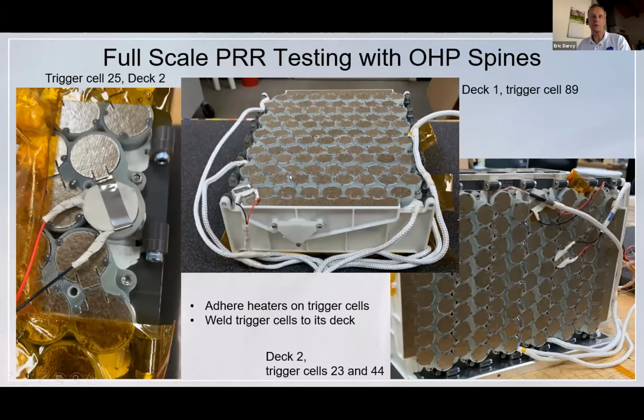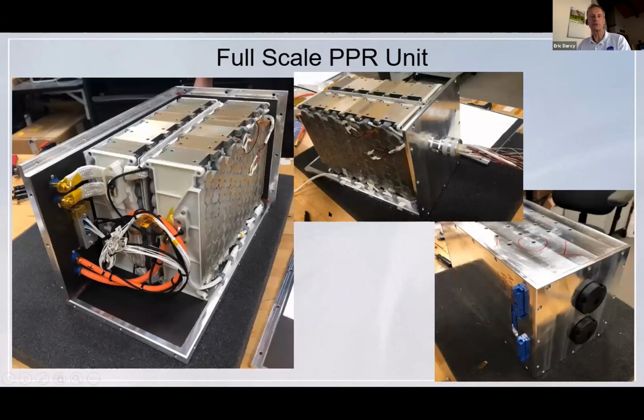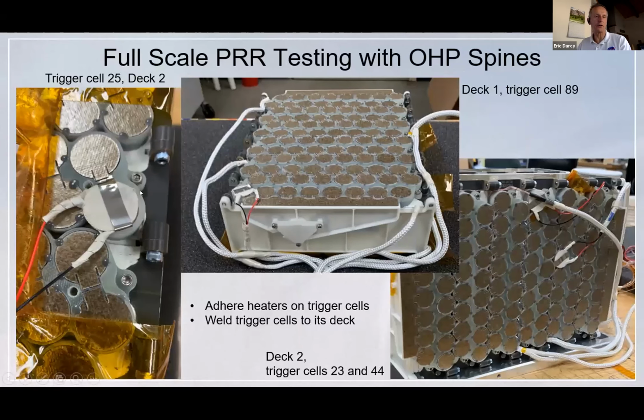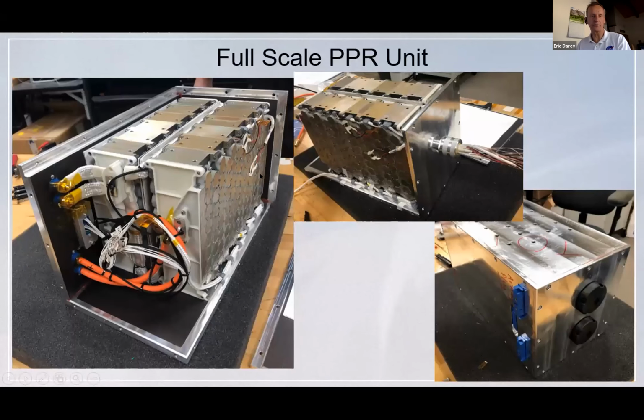As you can see here, we had some mica covers on the top of every cell, and that's so that when the trigger cell goes into thermal runaway, it blows through its mica cover, and mica is a very high temperature material. The adjacent cells then are protected from the ejecta. And here's our little homemade heater to heat up the trigger cell in order to drive the thermal runaway response without it heating all the other cells.